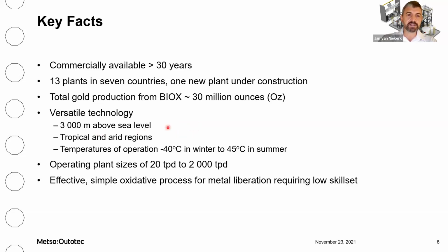It can be used in tropical and arid regions, and it can operate in temperatures from -40 to +45. Operating plant sizes range from 20 ton per day up to 2,000 ton per day. And it's really a simple and effective oxidation process for metal liberation, requiring a relatively low skill set.